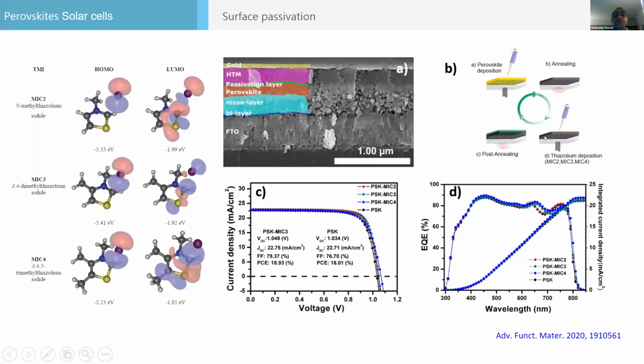In the meantime, we were also working parallelly. In thiazolium iodide, why we chose it, because its energetic levels were 5.55 electron volt, 5.41 and 5.23, very favorable to the conduction band of the perovskite. You can see the best one was 5.41, and that's why the MIC3 gave the highest value, because it was more favorable.